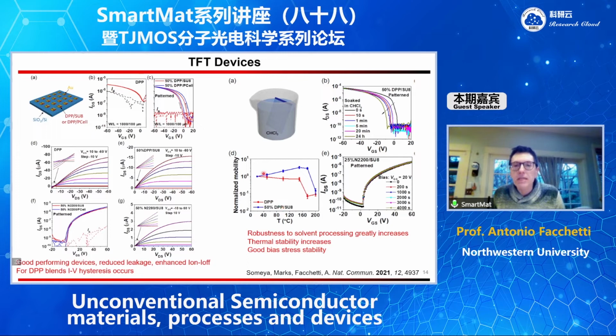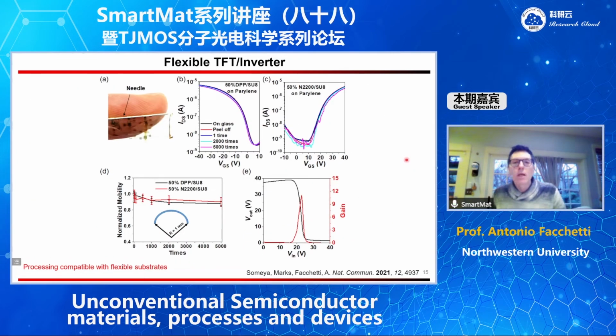Also, we check the thermal stability, and when the semiconductor is cured, the thermal stability is much better. And the bias stress is also quite good. And the process is also compatible with a very soft and flexible substrate. So we can pattern the P-type blend, the N-type blend, and check the bending, make inverters. The gain is not exceptional, on the order of 12, but this is a sort of proof of concept. So this is basically a different way to photo pattern the semiconductor, which is compatible with fab lines.